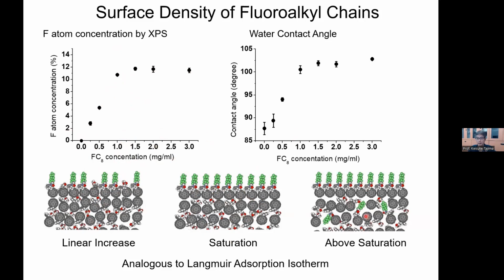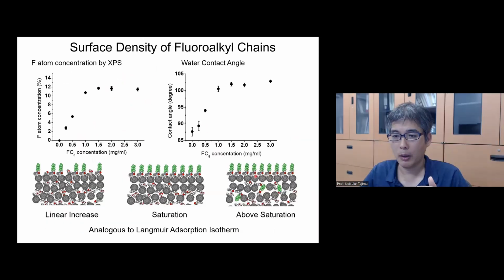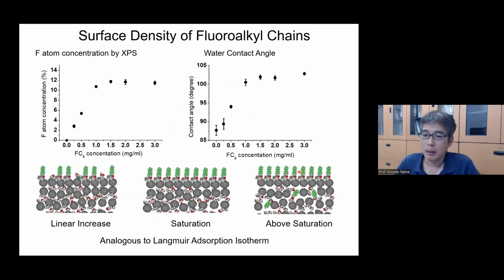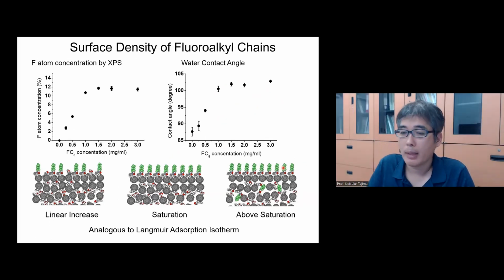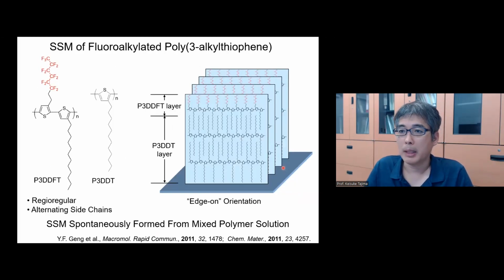Above that saturation, the surfactant has already occupied the surface, so it starts to remain in the bulk. This is the water contact angle of the surface, and you can see that the surface is getting hydrophobic. That is because of the fluoroalkyl chain exposed to the air, and there is a saturation here as well. So it's analogous to the Langmuir adsorption isotherm. Fundamentally, it's the same phenomenon. But the important point is that this monolayer remains on top of the solid film, and we can use it for manipulating the properties of the film.